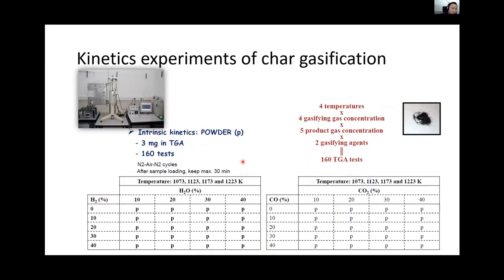The kinetics experiments of char gasification were done in TGA, and 3 milligram particles were dispersed in the TGA basket. A big matrix of TGA tests was made, and the effects of temperature, gasifying agent, steam concentration and CO2 concentration, and the effect of hydrogen and CO products were all considered. So around 160 TGA tests were conducted.